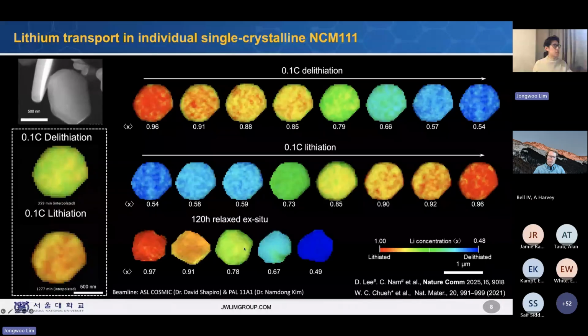However, what we see here is this lithium concentration is basically 95% flat. However, there's a 5% lithium fluctuation out there. What's going on? In order to understand these things, I want to assure that this is not defect associated, this is stress associated.